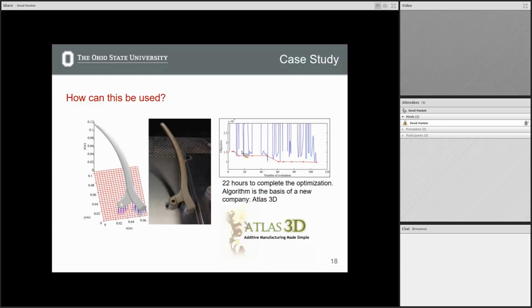This is the path it takes to find the optimal orientation. So what this is showing here, all the blue lines are this objective function, which, without going into the details, is primarily what is the distortion of the part. It's basically a metric of distortion with some other things thrown in there in terms of weights or penalties for having a temperature that's too high. And you see that most of the orientations it chooses randomly, it's not completely random, it starts to narrow down on better and better answers.